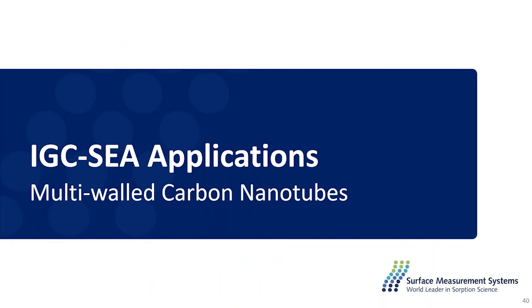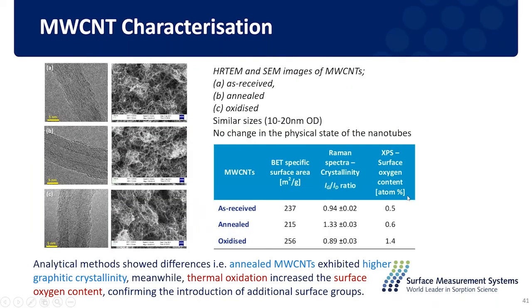And the last study I have here is for the nanotube again, but for another kind of characterization of different kinds of nanotubes. So here we have 3 different kinds of nanotubes. The as-received sample, a new sample modified with high temperature treatment at 2000 degrees for 2 hours. And the oxidized sample was modified by thermal oxidation using some chemicals, and it's also confirmed by the oxidation content by other techniques.